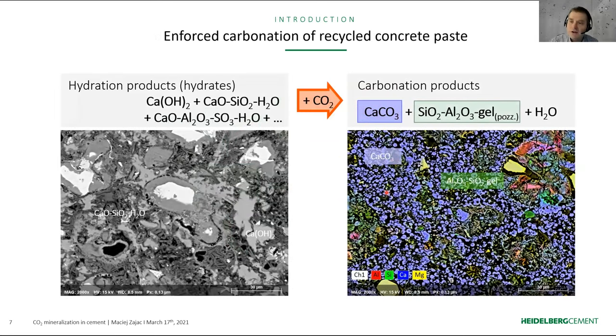CO2 mineralization when applied to hydration products, the so-called recycled concrete paste, is a more complex reaction compared to the first one that I showed you on slide number three. This is because in the fully hydrated cement paste, as is typical for old concrete, we have several hydrates, including calcium portlandite, CSH phases, and calcium alumina hydrates, including either ettringite, hemicarbonate or monosulfate. We find that all those hydrates react with CO2 to produce two main carbonation products, calcium carbonate and alumina silica gel. On top of that, this alumina silica gel is a pozzolanic material, allowing us to use this composite as a supplementary cementitious material.